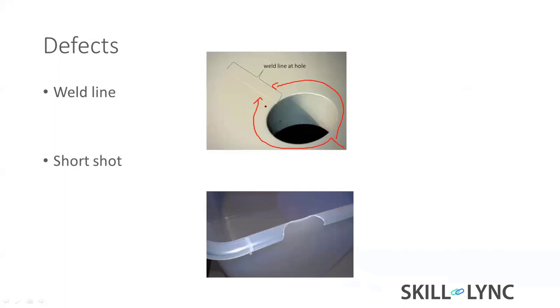Short shot - for plastic material, as a thumb rule, for generic processing you can go down to 0.8 mm wall thickness. Thin wall molding is also available but needs a special mold. For a generic mold, if you are keeping the part less than 0.8 mm, it creates short shots. Sometimes the part is too long and also creates short shots, due to material, design, and tooling factors.